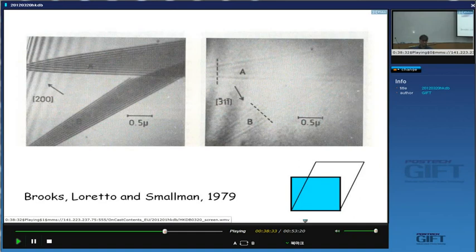Right? Similarly, in a stacking fault, if you do an experiment where g dot R equals 0, then this should disappear. And look, in this slide, it has disappeared. The contrast has disappeared. It's as if the stacking fault is not there. But notice very carefully, it hasn't completely disappeared. And the reason why it hasn't completely disappeared is because of the volume change normal to the fault.